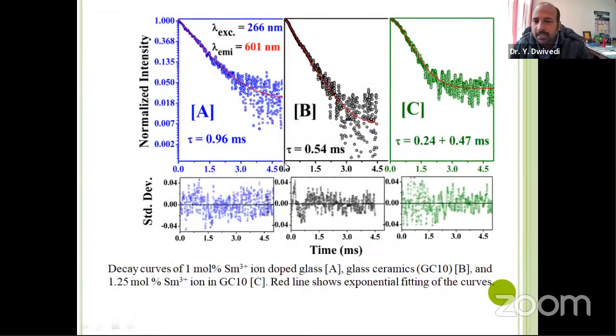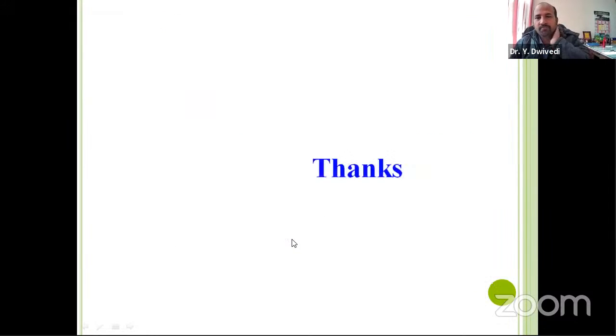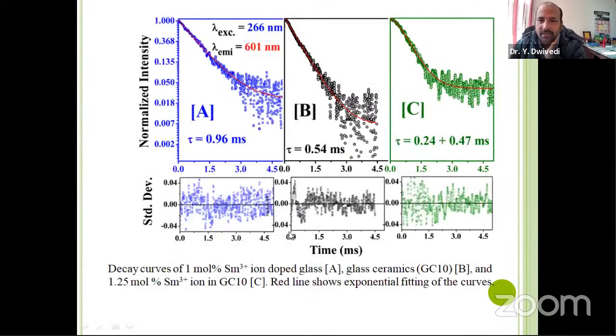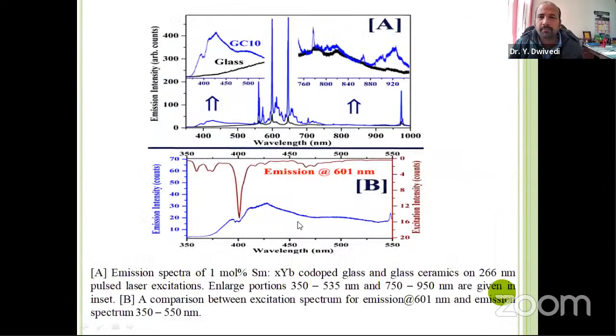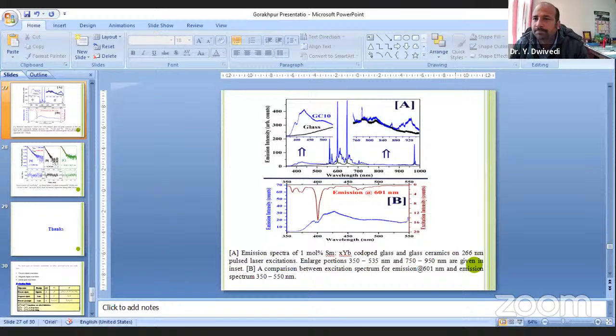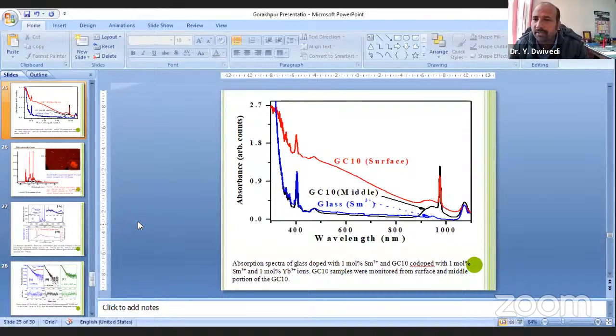So we also monitored the decay curve - like in case of microfibers, the optimized concentration was 1.25, but here in this case it is only 1 mole%, and the lifetime was around 1.22 millisecond in that case, but here it is only 0.54 millisecond. So this is a very important result, that at different micro-environments, we have different concentration and lifetime values.